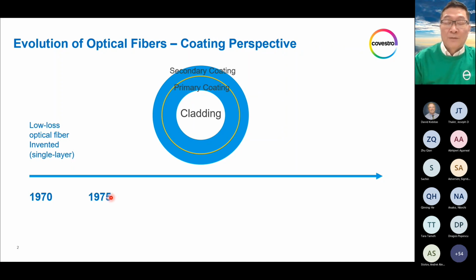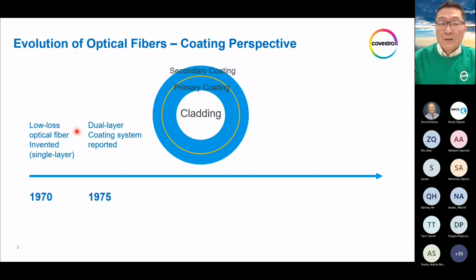Five years later, there was a breakthrough in 1975. It was reported that a dual layer coating system could significantly reduce microbending. So you remember the low loss fiber? There is a significant advancement over the 50 years. There is a relentless pursuit of lower and lower loss, part of the loss coming from microbending loss. After 1975, the current 125, 250 micron configuration took the mainstream, which means 125 micron in diameter for the glass cladding and 250 micrometer for the overall coated optical fiber, including both primary coating and secondary coating.